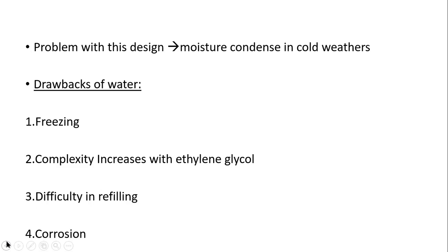If freezing is expected, water is drained from the collector tubes, but it is difficult to refill all the tubes in the morning. It is a big task. And another problem is corrosion. The continuous use of tubes with water causes the tubes to be corroded. And if the empty tubes are filled with air at night, it increases the rate of corrosion.